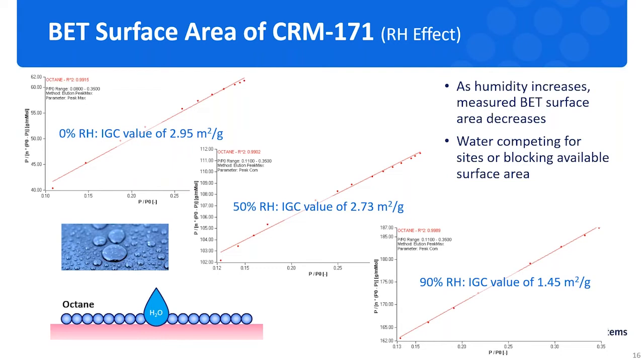But it also happens differently for different kinds of material. For example, for some cotton fiber or hair fiber, if the water can go into the bulk structure of that kind of material, then you probably will notice that the surface area is increasing with the humidity. So it's quite interesting to study this kind of humidity effect on the surface area of different kinds of material.